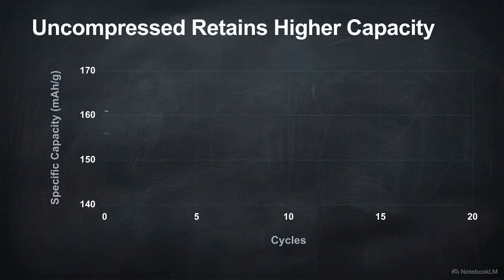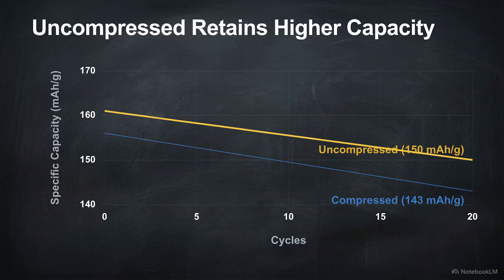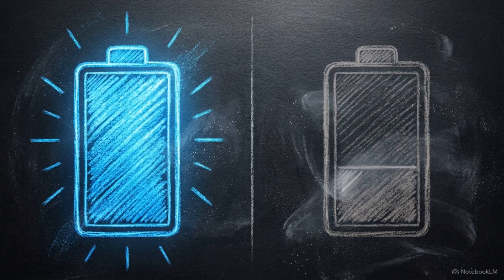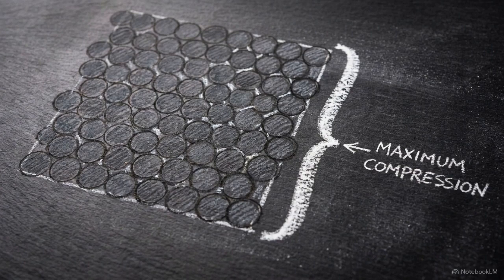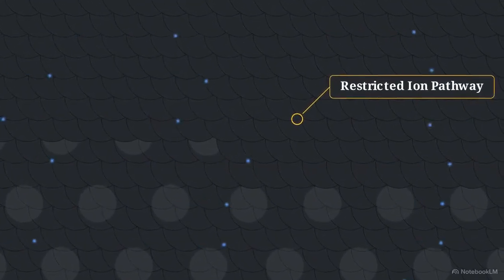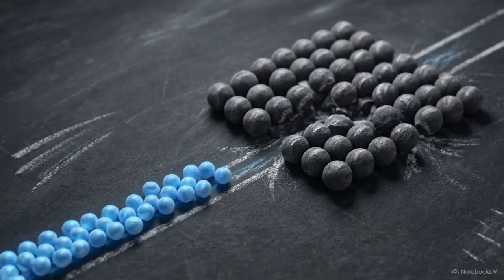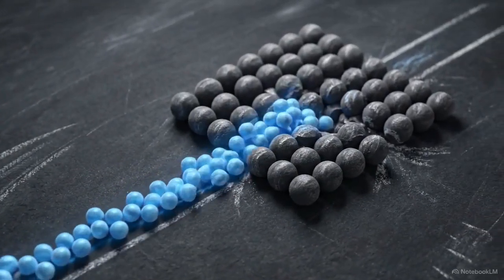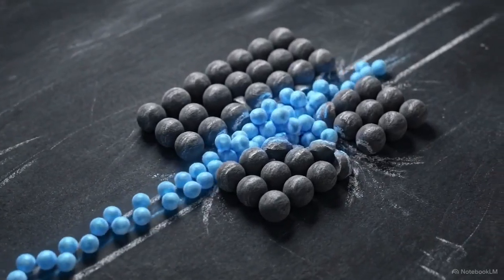This chart plots specific capacity, measuring charge storage per unit mass over 20 cycles. Counterintuitively, the uncompressed electrodes retain a slightly higher charge per gram. At the end of 20 cycles, the uncompressed samples hold at 150 milliamp hours per gram. The compressed samples fall lower to 143. This is the penalty of density. Calendering reduces the electrode's porosity to around 72%. This physically narrows the pathways required for lithium-ion diffusion, slowing the transport kinetics inside the battery. Optimizing the physical density for the manufacturing process actually creates a bottleneck for the internal chemistry of the final product.